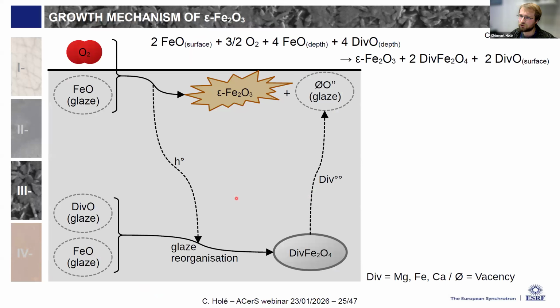Investigating the literature about iron-rich glass annealing, I could identify a potential mechanism that would explain the growth of epsilon. And this mechanism is based on the interaction of oxygen that is introduced in the kiln during the cooling with reduced iron in the glaze. And this crystallization of iron epsilon would actually leave the glaze with some, let's say, missing divalent ions, so it will be a bit less stable.